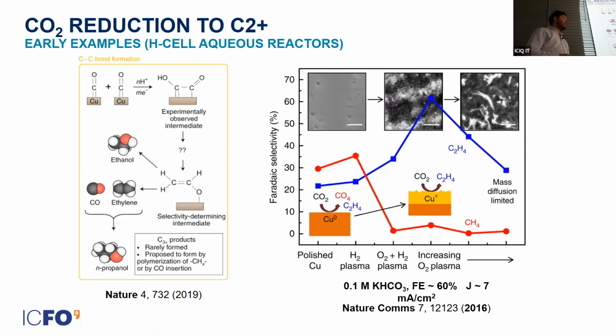We learned also that not only the element matters, it also matters how you make your catalyst. It matters if you make your catalyst using nanoparticles or you oxidize your catalyst first or not. In this paper, they've shown that depending on the initial oxidation state of copper, you could achieve high Faradaic efficiency approaching 60% towards ethylene, whereas if you have a different precursor, so you just have a non-oxidized metal, just pure copper, your Faradaic efficiency cannot reach high numbers for ethylene and can only reach moderate numbers for methane. In this early example, this was demonstrated in an H-cell type of reactor.